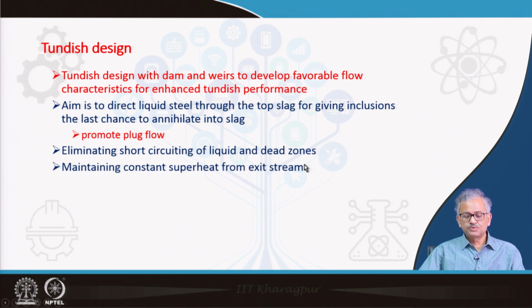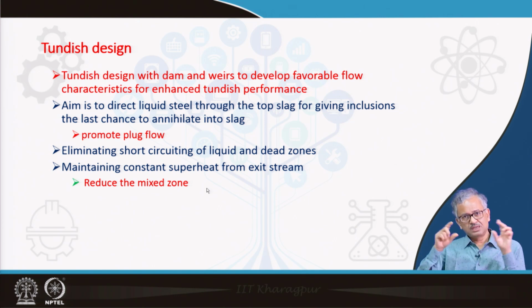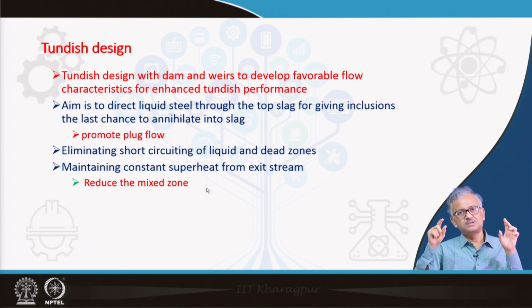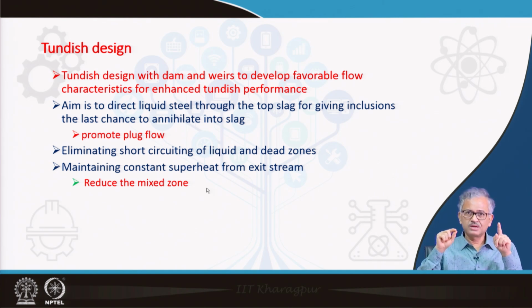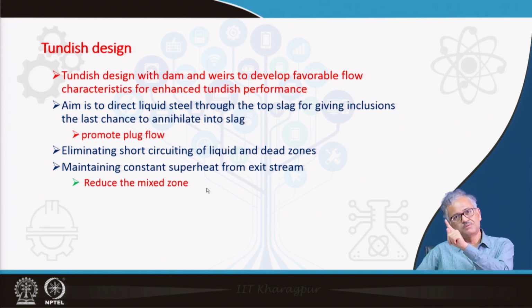Maintaining a constant superheat from the exit stream, as I said, you should avoid this type of short circuiting. And also reduce the mixing, that is very important, because any real reactor is a combination of ideal reactors like the plug flow reactor. In a plug flow reactor, the fluid moves at a constant velocity, so all the fluid elements have a constant residence time.